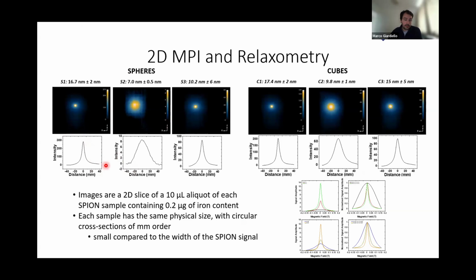We see exactly what we predicted. We saw very good signals for your large particles, really bad signals for your small particles by comparison, but much worse for spheres than you saw with cubes. So that's probably an anisotropy effect.